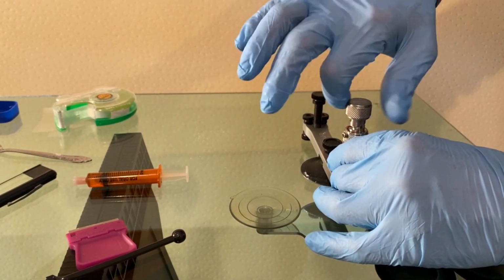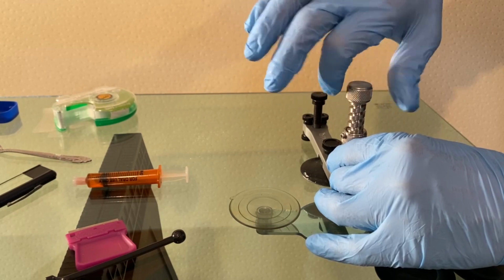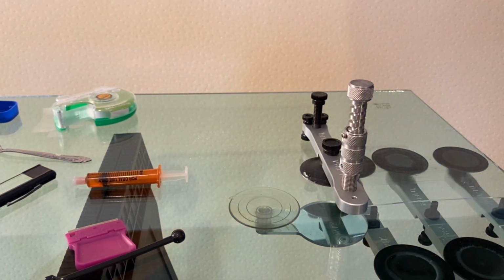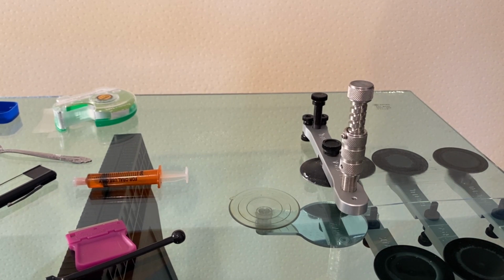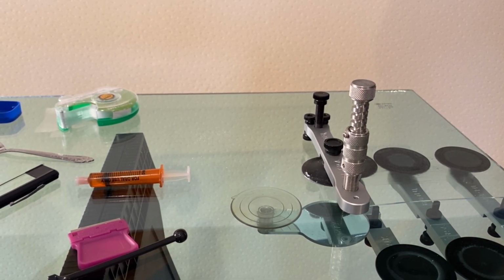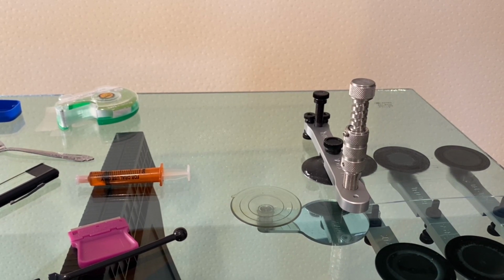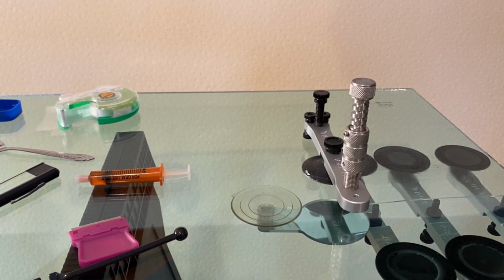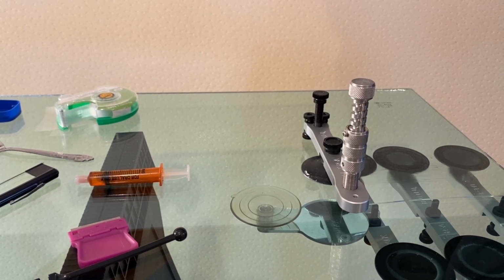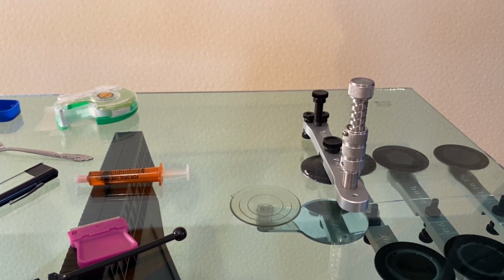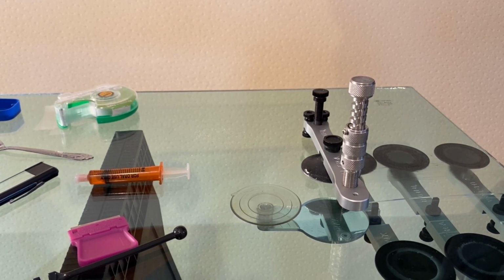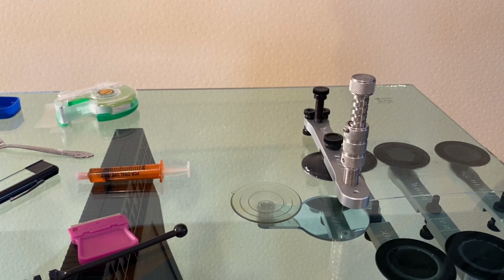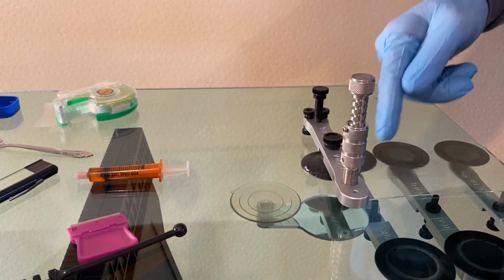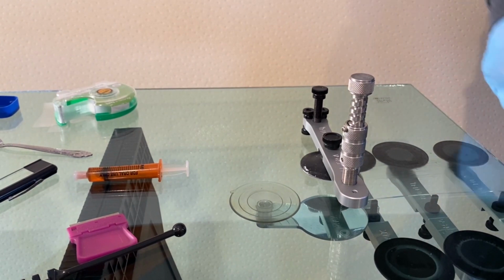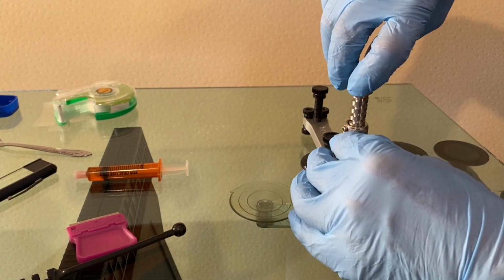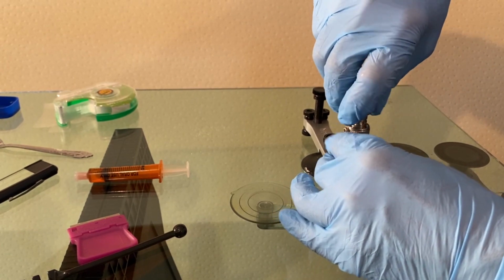Now what we do is that we do a second vacuum. And the purpose of the second vacuum is for wicking the resin. There is a very minuscule amount of air in a stone break or a drill hole, and it gets sucked out in a matter of seconds. The purpose of vacuum is for interaction, meaning you're moving the resin within the break, which causes interaction with it bonding to the glass, and then the wicking is getting the resin into all the microscopic crevices and craters inside that break. Okay, so now we're done with our second vacuum, and we're going to come back down to pressure.